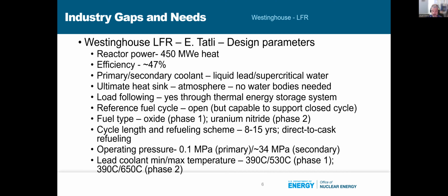Operating pressure, which is one of the nice things about the lead reactors, is quite low. It's only 0.1 megapascal. With their supercritical water, it's higher on the secondary. It's at 34 megapascal on the secondary. And the lead coolant min-max temperature, in phase 1, it's at the lower temperature reactor type. So it's 390 inlet, but 530 outlet. But in phase 2, they want to even push the higher temperatures, where you get into perhaps some more stringent creep issues, or even lead corrosion issues of going to higher temperatures. So there they'd like to go up to 650 degrees C in phase 2.